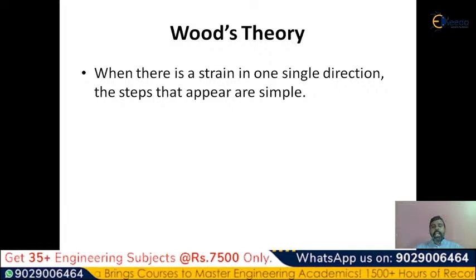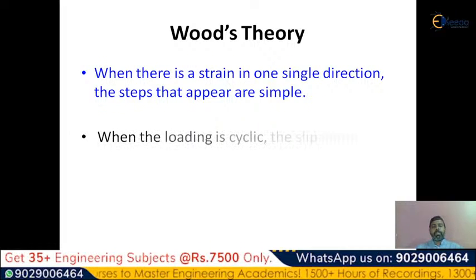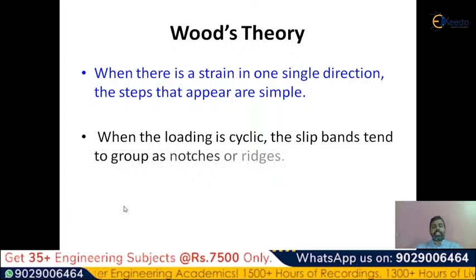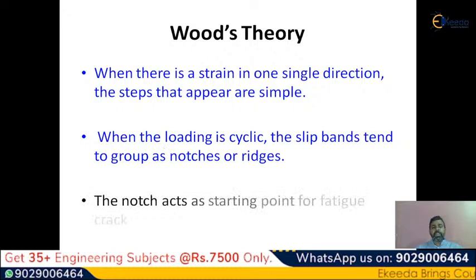If it is done again and again, automatically some problem may be identified. So that means when the loading is cyclic, the slip bands tend to group as notches. That means the slip bands themselves act as notches, as edges. Then from those notches, the crack is going to be generated. Wood says that due to the strain in forward and backward directions, the slip bands create the notches. Anyway, I will show it in the figure also.